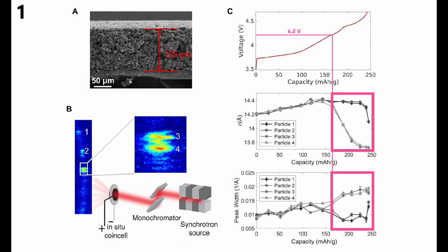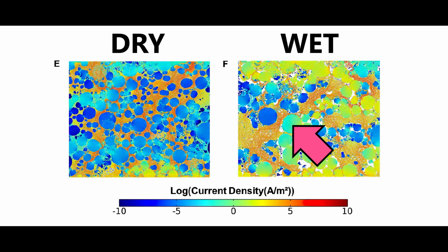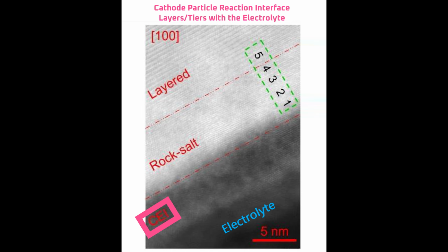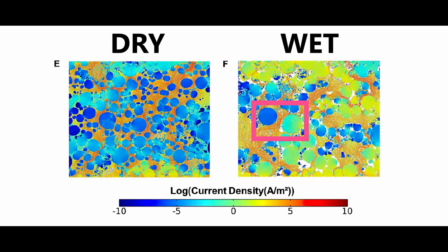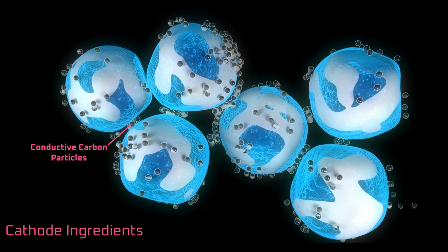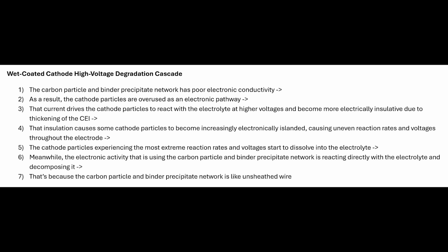But why do the voltage variations begin to appear above 4.2 volts in the wet-coated cathode? At higher voltages, the cathode particles, which are being used as an electronic pathway but shouldn't be, begin reacting with the electrolyte and form a thick cathode electrolyte interface, or CEI, that's an electrical insulator. That isolates some of the weakly connected cathode particles and forces more current through the well-connected particles, which increases voltage differences between particles and causes them to degrade more quickly. Meanwhile, the current moving through the exposed carbon particles in the wet-coated cathode reacts with the electrolyte at voltages above 4.2 volts, driving further degradation. For clarity, on screen is the high-voltage degradation pathway of a wet-coated cathode.